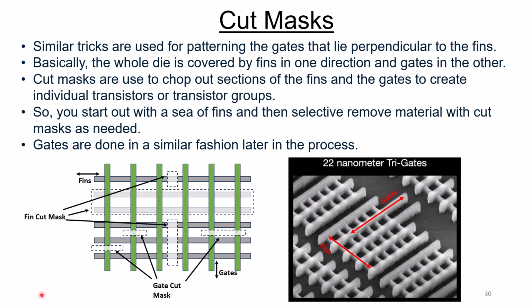So similar tricks are used for patterning the gates that lie perpendicular to the fins. So basically the whole die is covered by fins in one direction and gates in the other direction. And then something called cut masks are used to chop out sections of the fins and the gates to create individual transistors or transistor groups. So you start out with this whole big sea of fins and then selectively remove material with the cut masks as needed. And the gates are done in a similar fashion just later in the process.